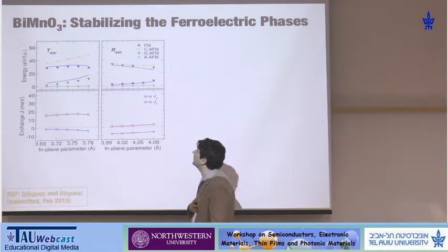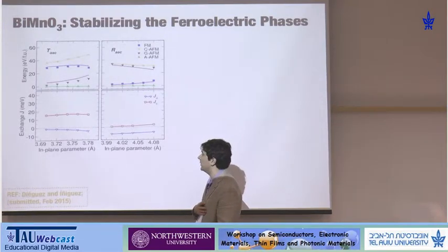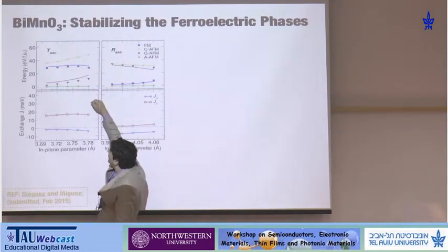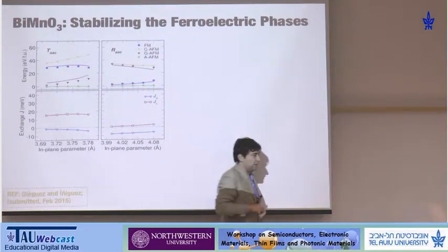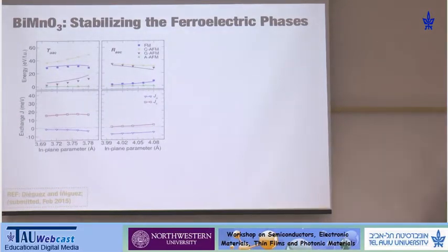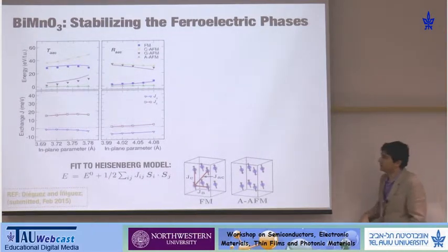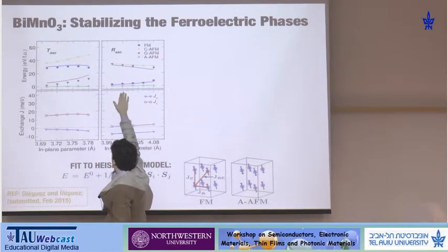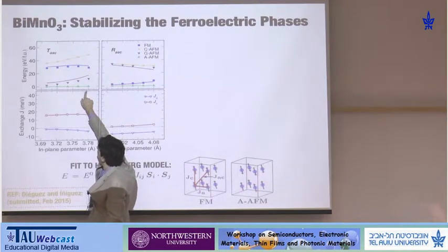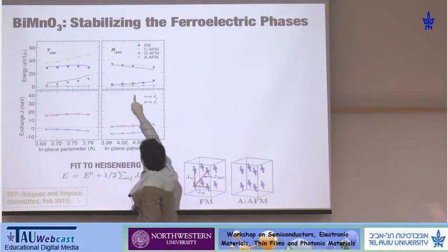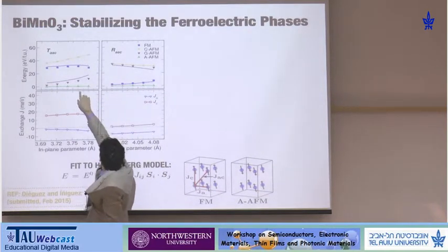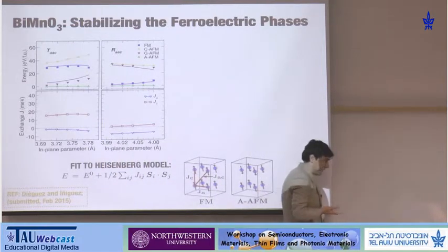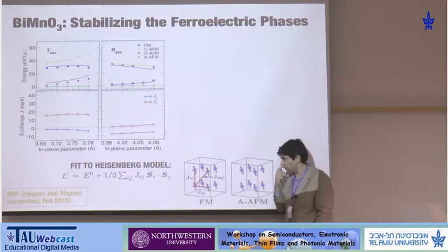I say maybe because we did calculations. We can also do calculations regarding the ferromagnetism, and we computed the differences between different magnetic arrangements. So for the 4 magnetic arrangements that I mentioned, for the super-tetragonal and the rhombohedral phase, we computed the difference between them. The one that is the most stable is one of the antiferromagnetic ones, but the ferromagnetic one is very close.